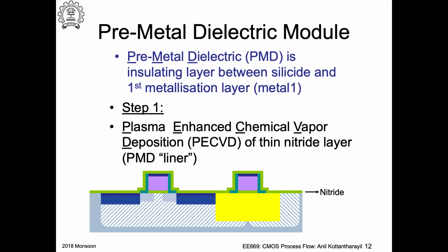The next step is to deposit the pre-metal dielectric module. Essentially you would deposit some dielectric layers on top before you put the metal, because if you put the metal everywhere, then I have a problem of short circuiting the gates. So the first thing is to deposit a thin nitride layer. It's okay to put it there because now there is no exposed crystalline silicon on top of the wafer. Everything is covered. You put this pre-metal dielectric by PECVD process, called the PMD liner.